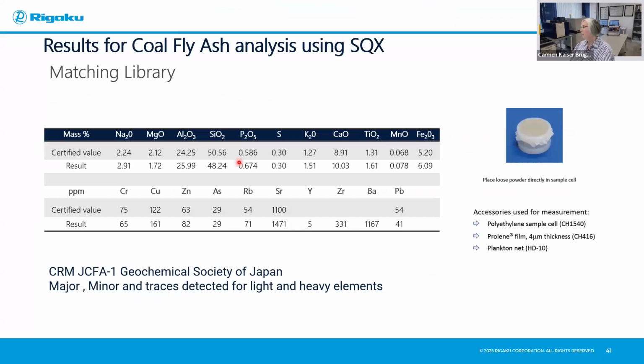Here we have another example using semi-quantitative analysis. This is quite a nice example, because we can use, for example, a certified reference material. And in this case, we used a Geochemical Society of Japan reference material. And of course, the reference material will always come with a certificate of analysis for the major, minor, and trace elements. So we can analyze the sample as a loose powder, for example, using our example that you see here with a film. So here you can see the details on how we prepared this.